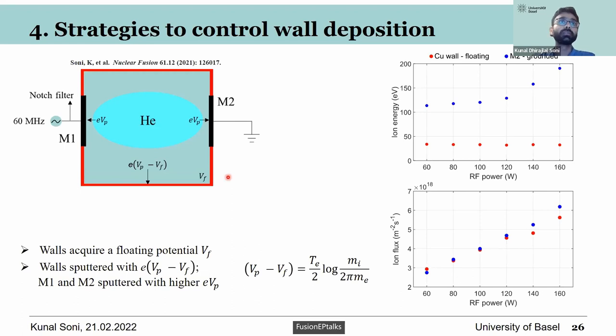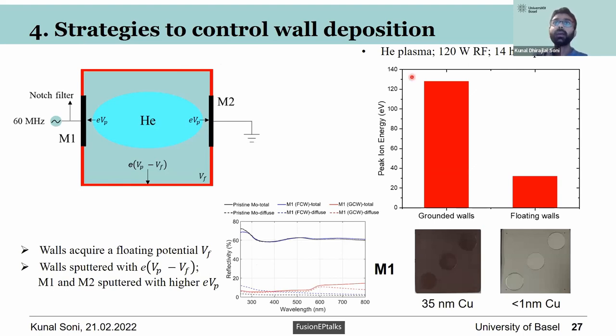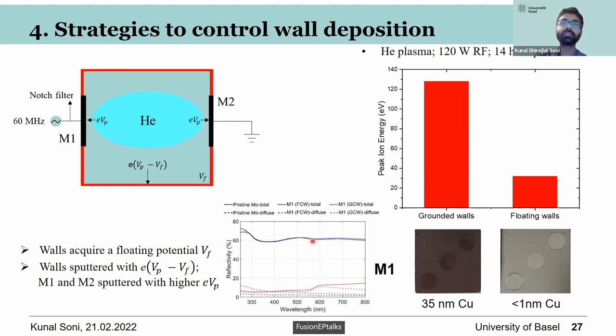The peak ion energy at the walls in the floating wall case is significantly reduced from 130 eV to near 30 eV — a 100 eV reduction — while the mirrors themselves experience no wall deposition. Measurements showed less than 1 nm of copper deposition on the mirrors, and their reflectivity was maintained at near-pristine values. This confirms that floating walls serve as a very effective mitigation strategy for mirror cleaning in the presence of a notch filter.